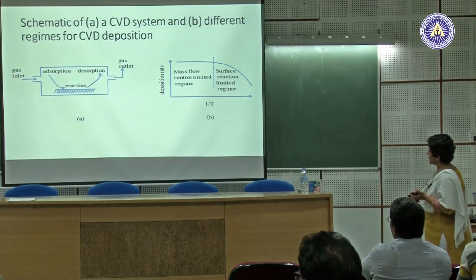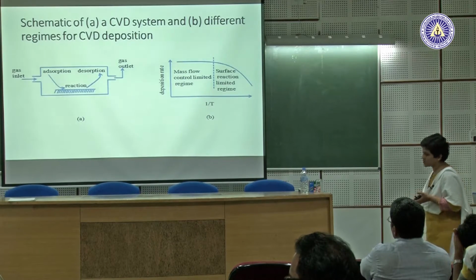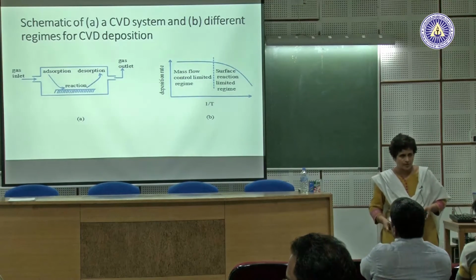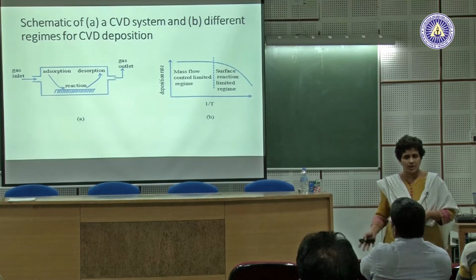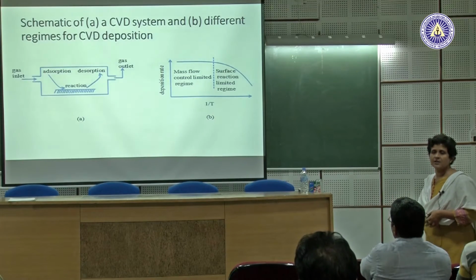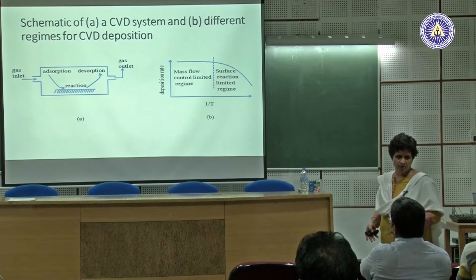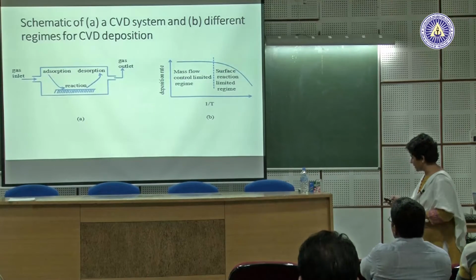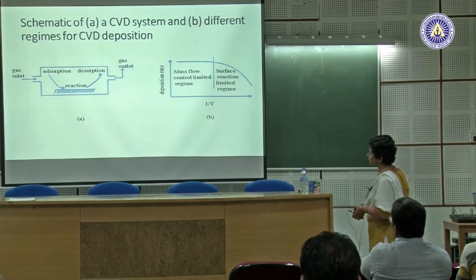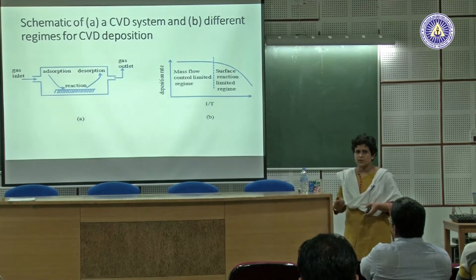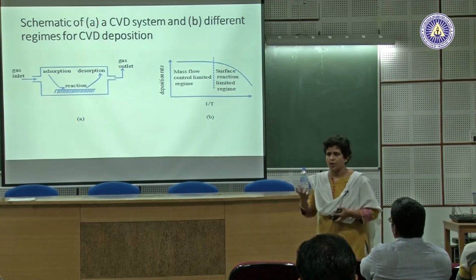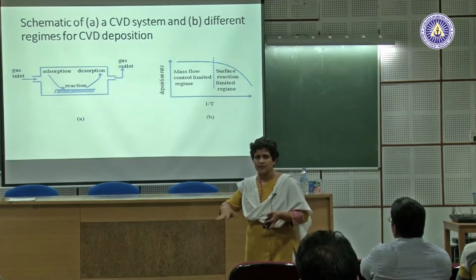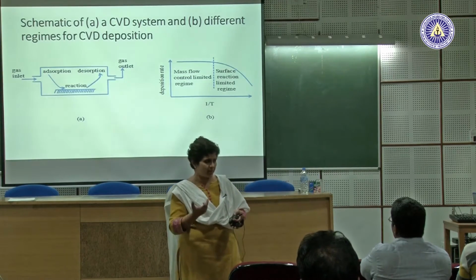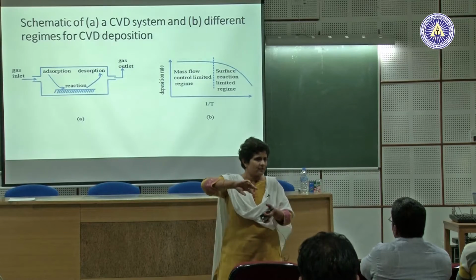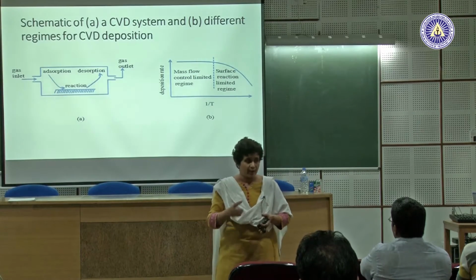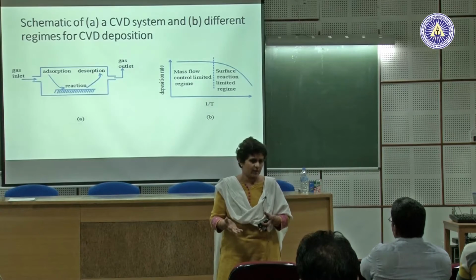If you have a deposition rate which is not dependent on temperature, you are working in the mass flow control regime of a reactor. If you have a deposition rate which is heavily controlled by temperature, then you are working in the reaction rate control regime of the reactor, right. So, that is the CVD process. Where is it useful? Think of a component you want to cover with a film, and it has a very intricate shape. It is not like a flat sheet, but it has 3D surfaces, and you want to deposit something uniformly on that surface.